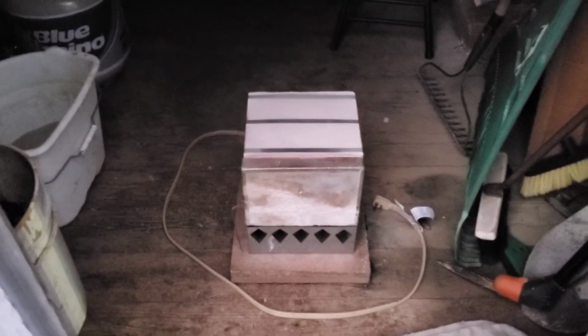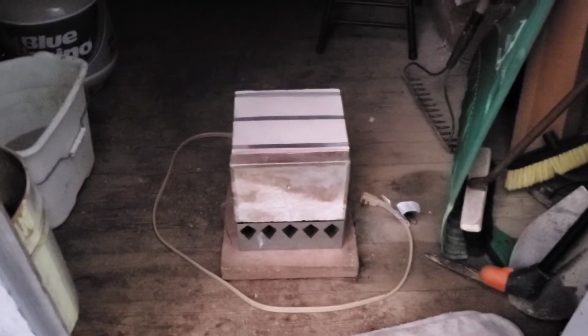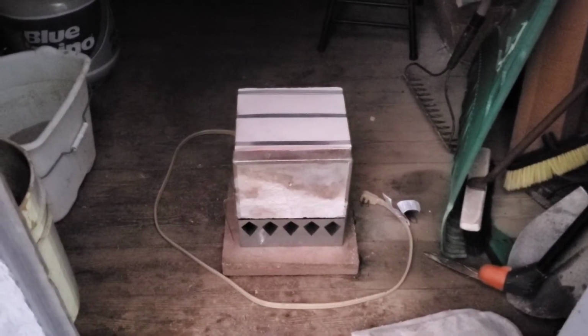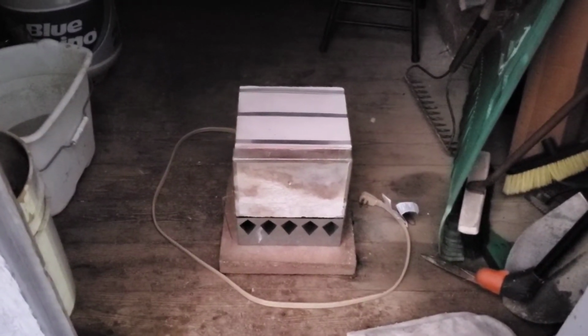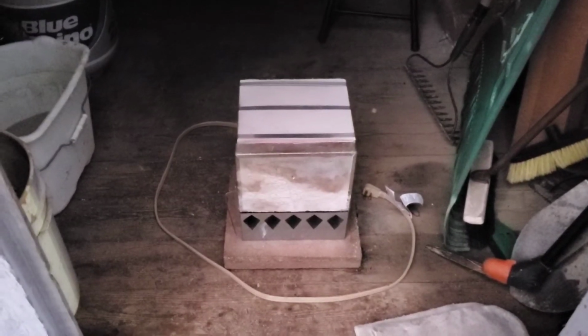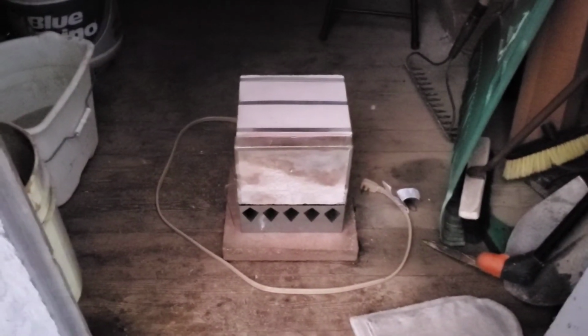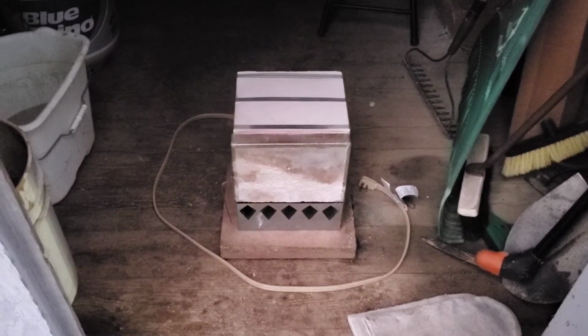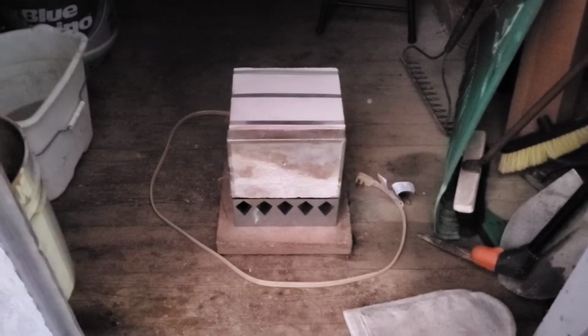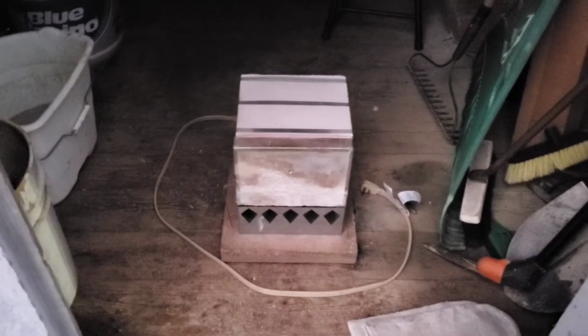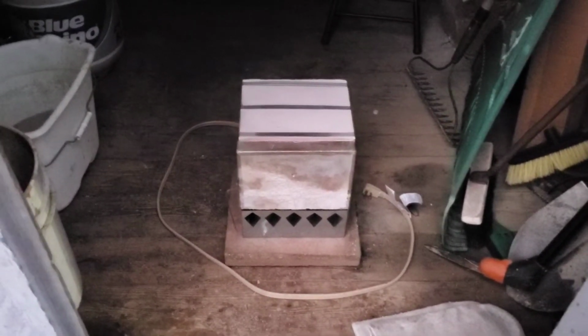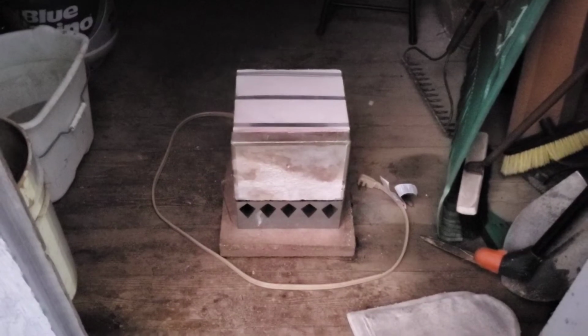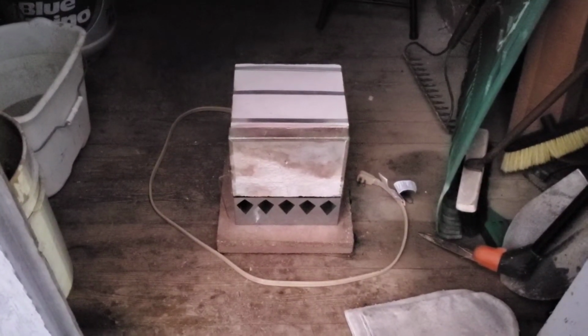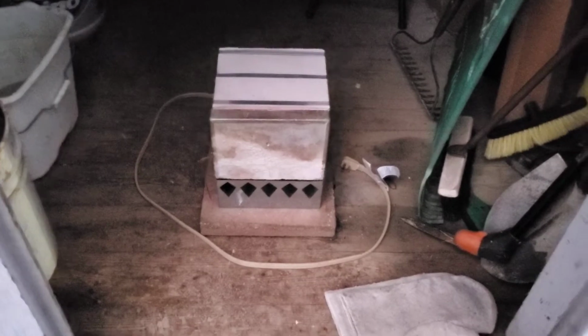That's why I wish I had the normal sized cones, because then I would get an accurate measurement. This is just a very rough estimate because all I had were the mini cones. So I'm going to let that sit overnight. Now, it definitely fired to ceramic temperatures. It fired to ceramic temperatures yesterday when none of the cones bent. But I'm guessing we probably fired up past cone 06, so maybe up to 05, I'm not exactly sure. But that's earthenware temperature. That's acceptable. So I will definitely be able to make some glazes.